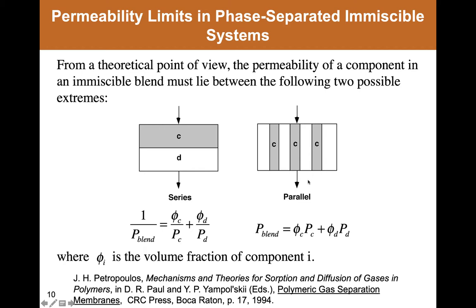And in this parallel transport model, it's straightforward to derive that the permeability of the blend is the volume fraction weighted permeabilities of each component. And any other arrangement of the two materials, that is of this phase separated blend, the transport properties will lie somewhere in between these two limits. And what this is headed for in just a moment is that the transport properties through a blend depend upon the organization of the structure of the heterogeneous material. And as that structure changes, then the transport properties will change.